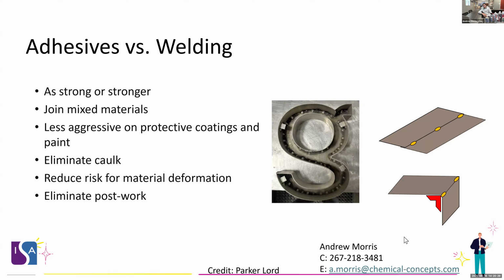Now, when I say as strong or stronger, this is an important point because often it's kind of apples and oranges. If you were to take two identical, just to keep it easy math, 1 foot by 1 foot squares of metal, and put two squares like that together in a butt joint or a lap joint, and you were to do a continuous weld and compare that to a continuous bead of adhesive, completely like for like, and try to pull both of those things apart in a machine that measures the force to separate them, that weld would probably be stronger. But often when we're replacing a weld with adhesives, we're not replacing a continuous weld. We have to design things differently for adhesives.